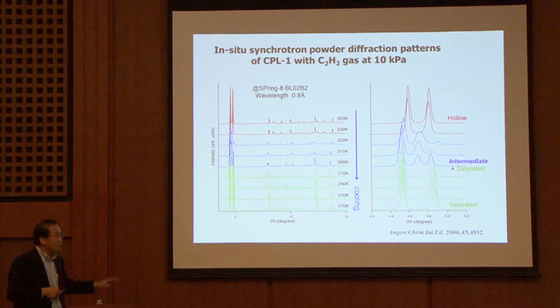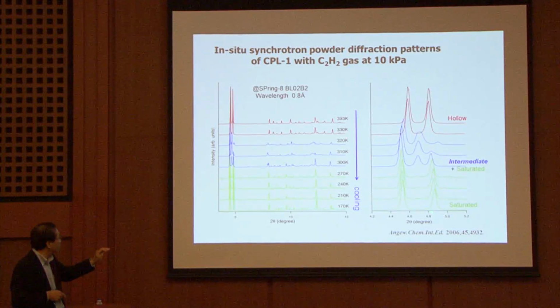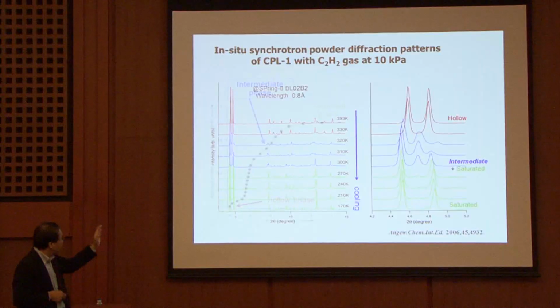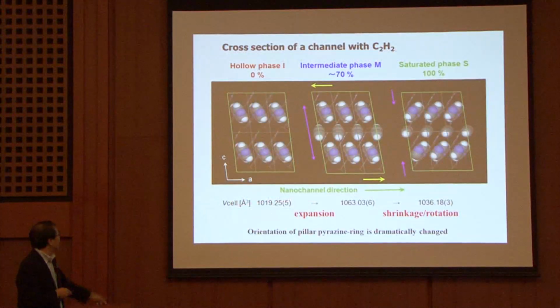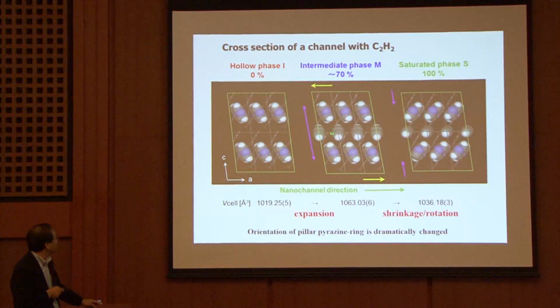So what happens in this case? Okay, these are the diffraction patterns. We observe the initial structure and the final structure, and we also observe the intermediate phase. So we determine the crystal structure. That is the result. This is the direction of the channel. This is the pillar ligands. And this is a vacant form, and 70% acetylene accommodated. So this is 70% occupancy here. And then this is 100%.